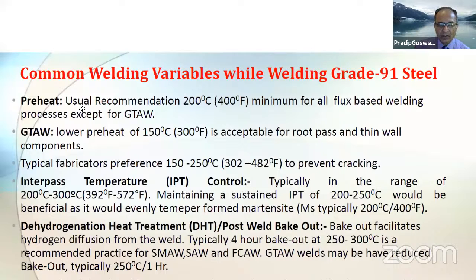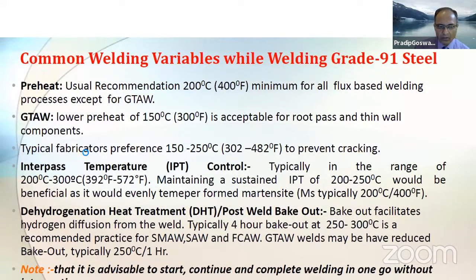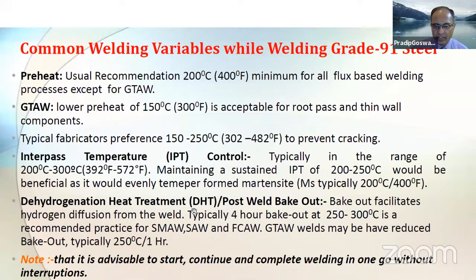This is typically what are the different preheat, interpass, and dehydrogenation treatment required or recommended for this steel. Now, with respect to this steel, there is a term called dehydrogenation or DHT, or post-weld bakeout. Now, as I mentioned earlier, sometimes the fabricators may not be in a position to perform post-weld heat treatment immediately after welding. Under that case, what should the fabricators do? It may be risky, considering the fact that the welds have 350 or even 400 Vickers of hardness. What is recommended is that as a minimum requirement, a DHT, or post-weld bakeout, should be done.